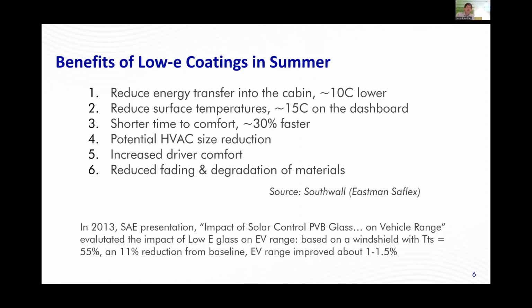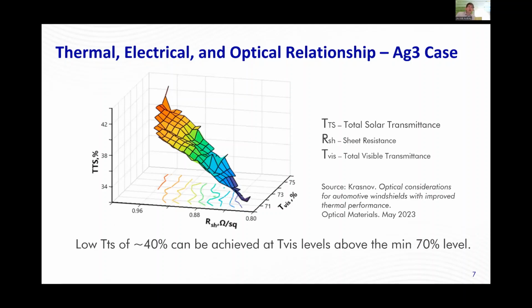And one example that I'd like to show, this study just came out from Alex Krasnov and was published in Optical Materials this month. This is very interesting because it shows the thermal, electrical and optical relationship using triple layered silver. You can see TTS on the left side, sheet resistance on the bottom, and then on the third axis, you see the visibility, the amount of visible light that passes through. And you are seeing TTSs of even below 40% are being shown to be possible now. And these are all being shown to pass through 70% of the TVIS.